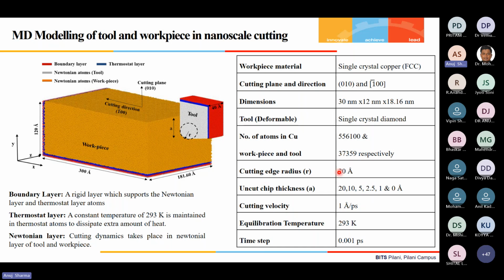The cutting edge radius is around 0 angstrom. The chip thickness is varied from 2 nanometer to 0 angstrom. Cutting velocity is around 1 angstrom per picosecond. The equilibrium temperature is around 293 Kelvin. That means this cutting has taken place at 20 degrees Celsius. And the time step is 1 femtosecond, that is 0.001 picosecond.